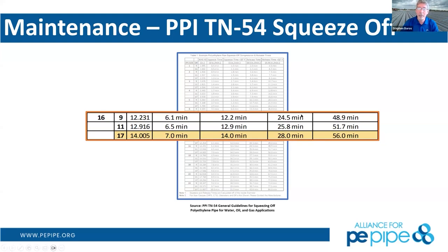during that release. So normal release time above 32 degrees will be 1 inch, or excuse me, ½ inch per minute, resulting in almost 25 minutes just for the release time on that 16-inch pipe. If you're below 32 degrees, you have to double that again, and you're going to 1/4 inch per minute, up to 50 minutes or 49 minutes to release that squeeze to make sure that you don't damage it. All this is detailed within this document. If you follow those procedures, you're not going to have a damaged pipe, and it won't be an issue.